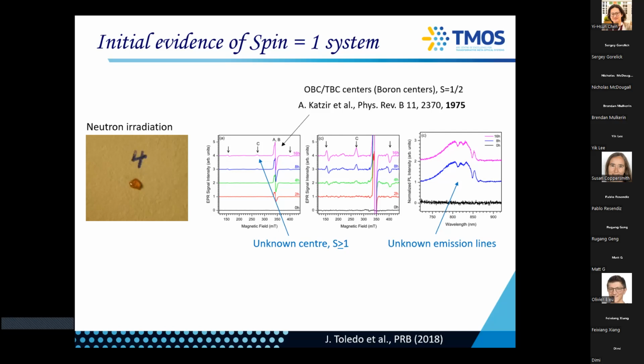And when you do EPR, you actually see this line, the split line, very strong. It's a spin half defect. Based on my personal research, this is the oldest EPR signature of any solid. It goes back to 1975 from Katzir. That was observed. It's, yeah, basically here. It was here from 1975. It's correlated to the OBC and the TBC. It's 1 boron center and 3 boron centers in hBN. They are not optically active, boring.